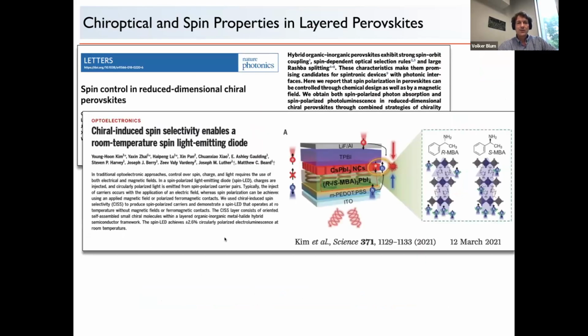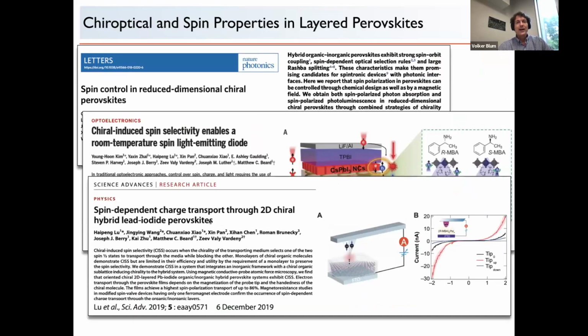This has been used in even a diode that was made by our colleagues at National Renewable Energy Lab, and also in spin transport. So you can basically take a chiral perovskite layer, get spin up carriers, they go through just fine. Spin down carriers will be blocked. So these are actually spin filter materials as far as something called the chirally induced spin selectivity effect. And so this is quite exciting for the spintronics oriented community.